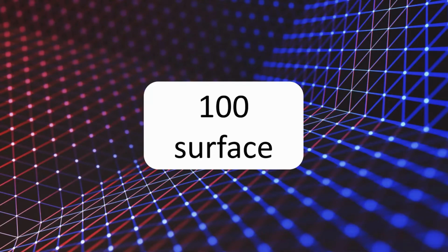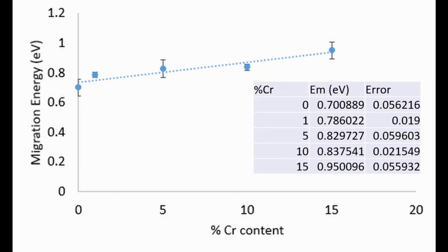Many simulations later, I was finally able to plot the migration energy versus different concentrations of chromium, as well as migration energy versus layers of chromium for each surface. For the random cases in the 100 surface, we noticed an increase in the migration energy from about 0.7 to 0.9 eV. A higher migration energy means the atoms need more energy to move, so it has less mobility. Therefore, as the chromium concentration increased, the mobility decreased.